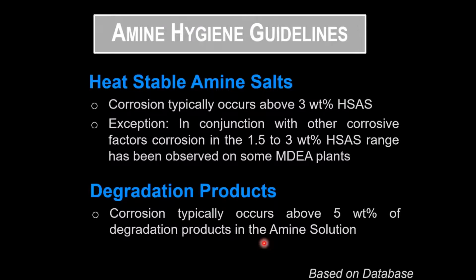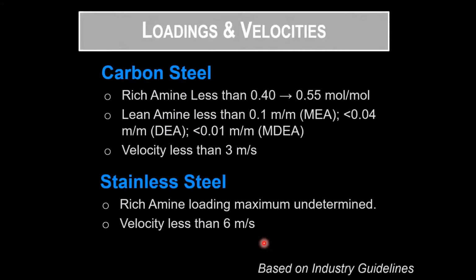That's why many of us have gone to MDEA, because MDEA is the most robust amine against CO2 attack, because there's no direct reaction pathway between MDEA and CO2. We've got some loadings and velocity guidelines. We want to make sure that our solution is properly stripped. If we leave too much H2S or CO2 in our lean solution, then our lean piping can be corroded, and we want to make sure that doesn't happen.